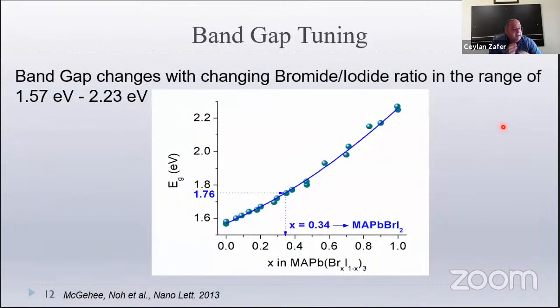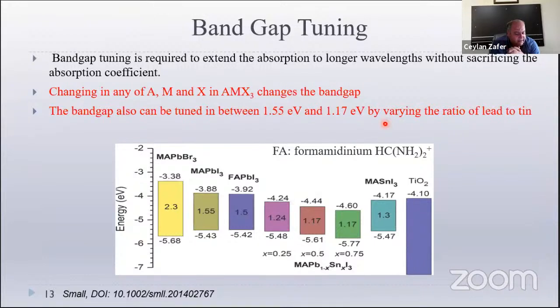that can be modified by changing the stoichiometry of the composition, like the stoichiometry of the halogen. If you change the stoichiometry of the halogen and add another one instead of the iodine, it can be replaced with bromine, and the band gap changes very precisely, and we can harvest more energy by optimizing this ratio. On the other hand, we can play with the central metal as well as changing the stoichiometry of the halogen. Here you see that by changing the cation, it also changes the band gap, the optical band gap, starting from the methylammonium lead bromide